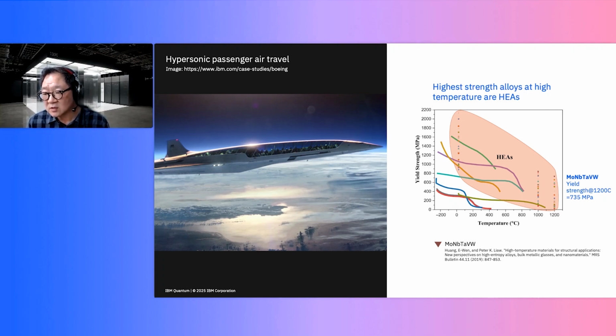And most of them are nickel alloys. Inconel, for example, are the purple and green lines. And you can see that they start to bend down at around 700 degrees C, and they're losing yield strength. They're losing stiffness. However, there's an interesting class of materials called high entropy alloys, or HEAs, and you can see those in the various points at 1,000 degrees and 1,200 degrees. These are alloys that are retaining their structural strength even at high temperatures like 1,200 degrees C.